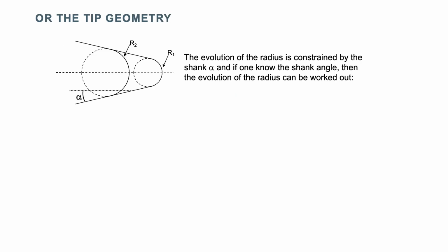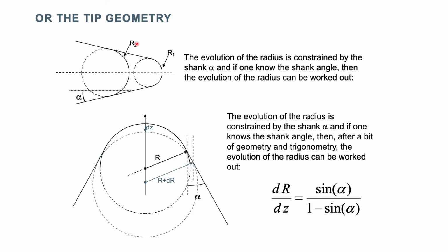The other alternative is to use a constant shank angle, for example. And then there is a direct relationship. Every time you detect an ion, you go in depth, you can recalculate the new radius of curvature, assuming a certain shank angle. In IVAS, there are also a number of options to use, like the tip shape and those types of things.